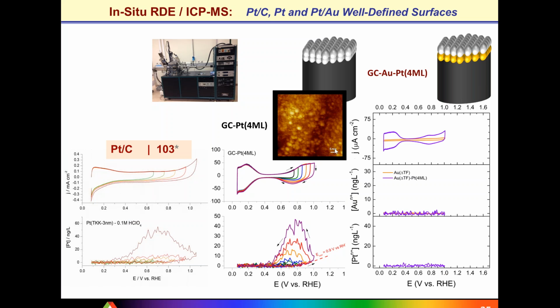And here is the case when we use the same film thickness of platinum, 4 monolayers, but what is different, we put several monolayers of gold in the subsurface. So in other words, the message to take home here, we can indeed influence this to a high level. We can completely diminish the dissolution of platinum by introducing gold in the system. Of course, gold is not the most desirable element to put because it brings additional cost. However, here we are looking into a few atomic layers of gold and platinum that are positioned in a very distinct way, and by doing so we can completely diminish and get rid of platinum dissolution.